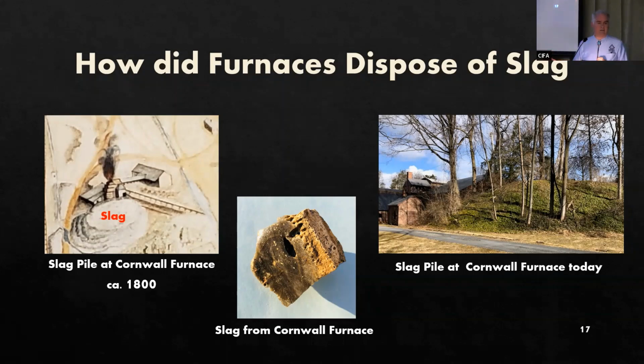First of all, notice how glassy it is. So again, that's pretty typical for a charcoal fueled blast furnace, that the slag is more glassy. Second, note the rind that's on the bottom of the slag, which is actually on the top of this picture, just to illustrate it. You can see, if you look closely at that slag, where it cooled, sitting on top of the sand. And then on the very top, you can see how glassy it is. It's because the slag on the top in the air would have cooled much faster than it would have cooled on the contact with the sand. And so on the bottom rind of that piece of slag, you can actually see little crystals of those minerals that we talked about before, because they had more time to grow in that piece of slag than they did at the top of the piece of slag. You can also see how those gas bubbles were trapped by the very glassy slag.